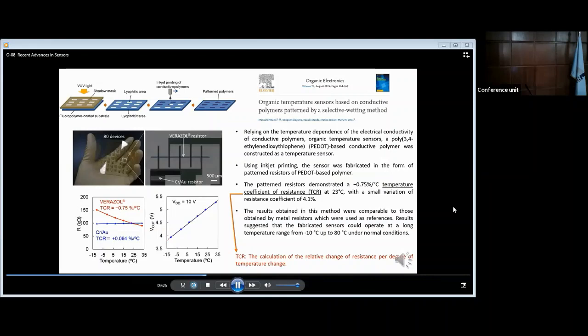The paper is titled Organic Temperature Sensors Based on Conductive Polymers Patterned by Selective Wetting Method. This study examines the temperature dependence of the electrical conductivity of conductive polymers. Organic temperature sensors based on the polymer poly(3,4-ethylenedioxythiophene) as a conductive polymer were constructed as temperature sensors.